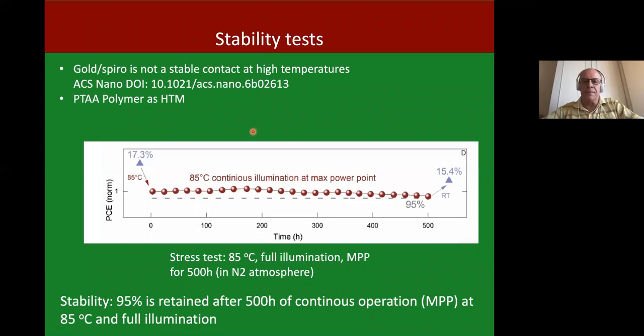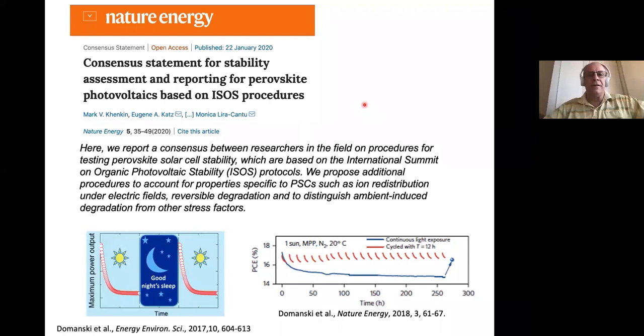So that's very promising stability data. You see also something interesting here, that at the end when we switch off the stability measurement and let it rest for a while, we also jump back a little bit in efficiency, which is a very intriguing effect of perovskite. So here I would also like to advertise Mónica's paper, and there are, I think, something like 60 people on